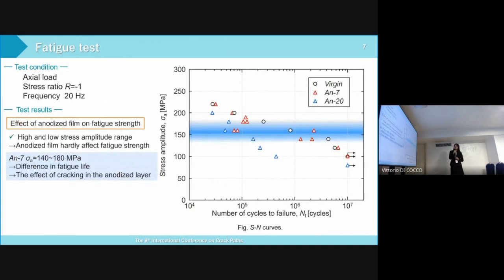Next, this is the fatigue test result. In this study, axial load fatigue tests were conducted at stress ratio R equal to -1 and frequency F equal to 20 Hz at room temperature using a hydraulic servopulser. The black circle shows the result of bare, the red triangle shows the result of AN7, and the blue triangle shows the result of AN20.